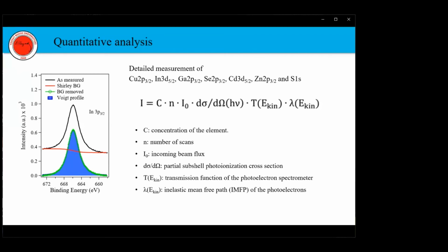The normalization factors are listed here. C is the concentration of the corresponding element. N is the number of scans. I0 is the incoming beam flux. Sigma, partial subshell photoionization cross-section. T is the transmission function of the photoelectron spectrometer. And finally, lambda is the inelastic mean free path of the photoelectrons.